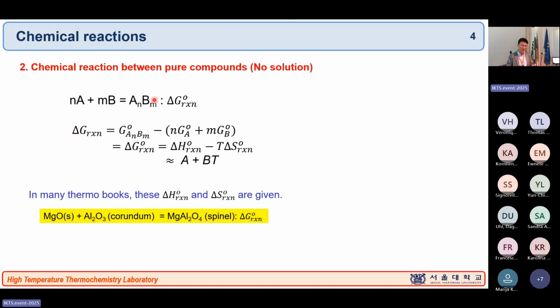In this case, it is product Gibbs energy minus reactant Gibbs energy. And the product AB is in the pure state, so G AB naught, and then G A naught, G B naught. Then you can get this, which is the same as this value, and which is typically expressed in the textbook as A plus BT, because enthalpy minus T times the entropy term. And within a given range of temperature, this value is almost constant. That's why we typically express it as A plus BT, but theoretically, this can be more complex than that.